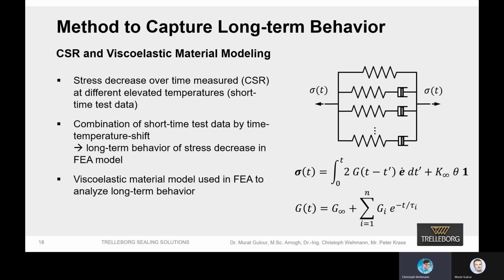So when we wait a very long time, that's the resulting stress response. And in between, we will have dashpots which have different relaxation times. That means they will relax in a certain time, and we have a spectrum. So in the beginning, some of these will relax and then others. So we use such a model to do FEAs, finite element analysis, to predict the lifetime of a seal or an elastomer part.